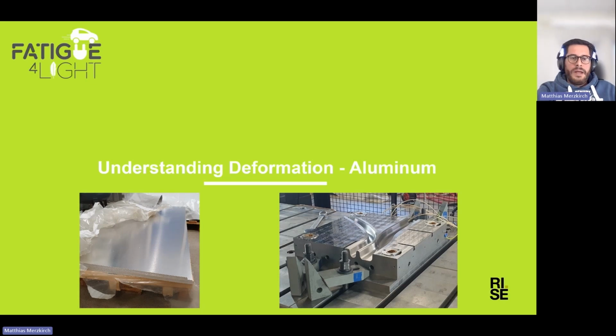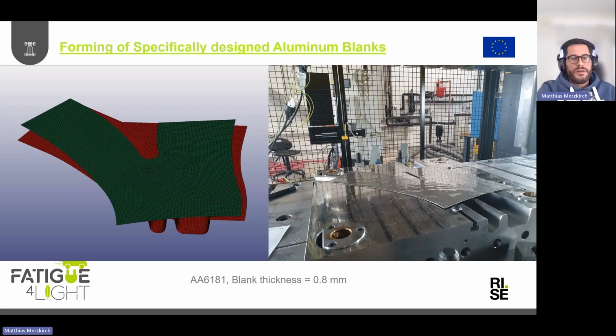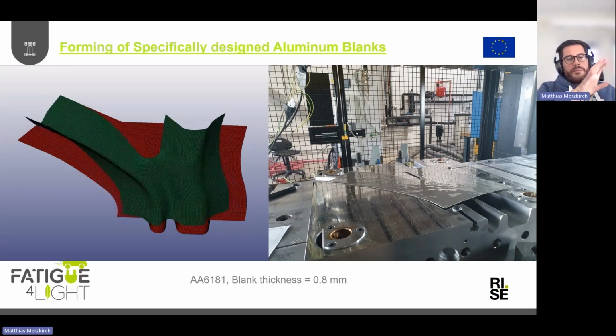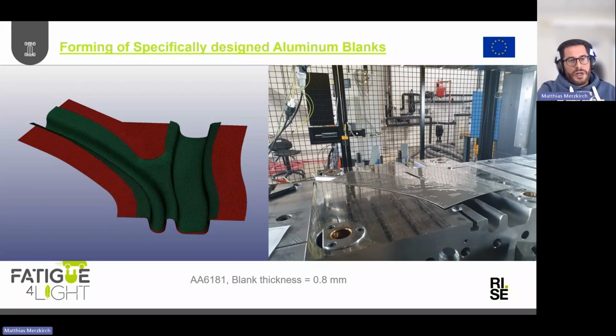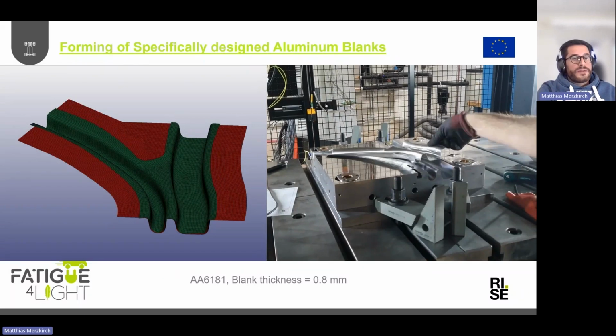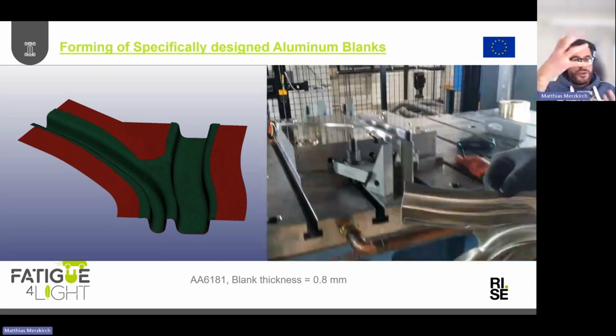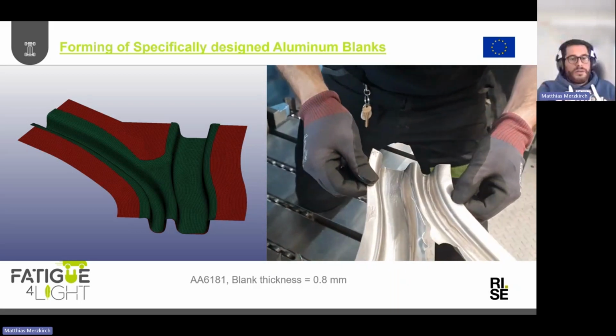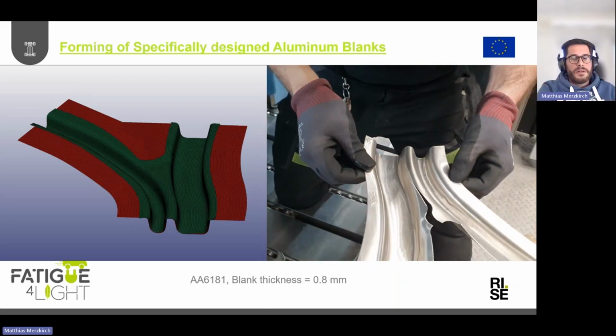this complex shape. And now coming from the composite side, the fibrous composite side, we also have to understand a little bit about the aluminum. This is a video that you actually saw in the beginning. So at some point there was a forming simulation done by Abaqus in order to understand, okay, what is actually happening? What is the shape of the material, the blank thickness of 0.8 millimeters. And what you see here is, well, cracking occurs. How and why does that occur?